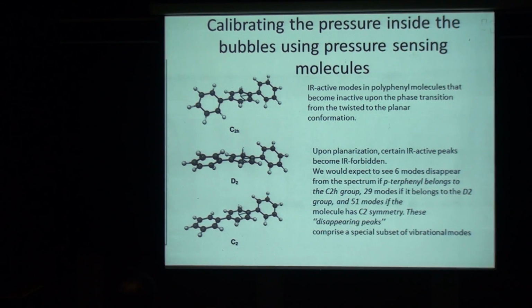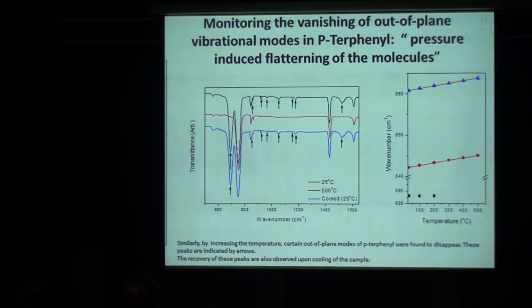So the experiment is very simple. These molecules show infrared active vibrational modes when twisted out of plane. The moment you bend it in plane, these IR active modes will disappear. So I just need to put these molecules inside the bubble, heat up the bubble and see when the infrared active modes disappear. At the point where it disappears, it must have a certain pressure inside the bubble. So this is the experiment. True enough, we put these molecules inside the bubble and then we perform an FTIR experiment to monitor when the peak disappears.